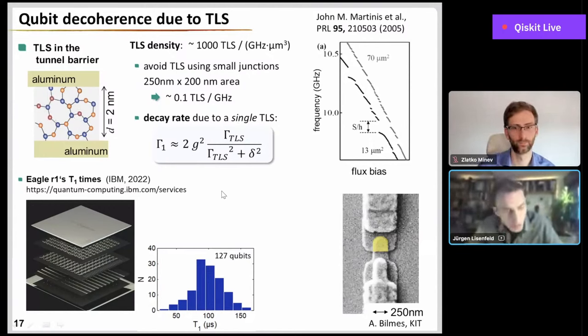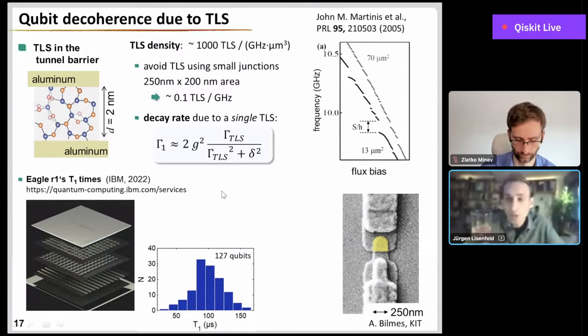But it's also true that, of course, this may just be bad luck, maybe. If you look at measurements of glasses, then, of course, you can get better statistics on the lifetimes, for example, if you just measure how long it takes for glass to cool down to low temperatures after you have fired up your fridge.